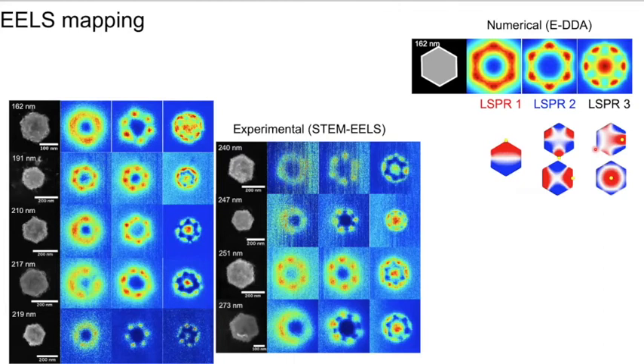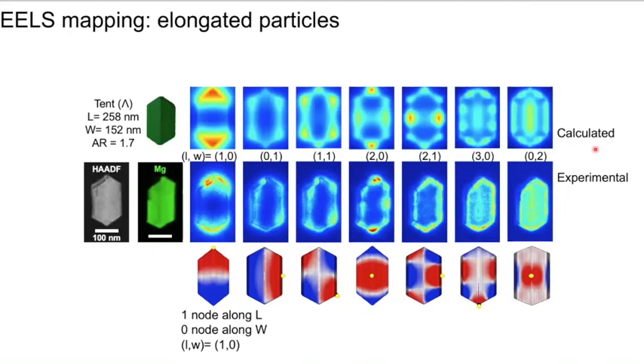The modes are not necessarily at the same energies because, of course, size matters. But in terms of mode distribution, this is very repeatable. We've then started looking at our elongated particles. Remember, these are basically hexagons that are folded and have elongated a little bit, and so that should break the symmetry.